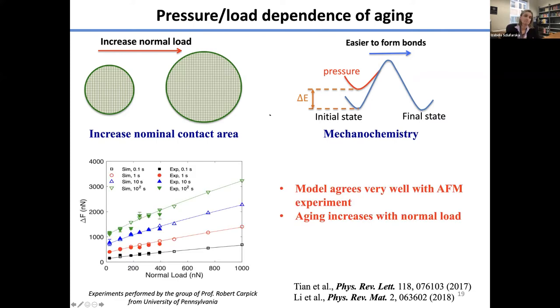So we included mechanochemistry. We have also included the fact that if we have a single asperity and we increase the normal load, the nominal contact area is going to increase as well. So we're going to have more of these bonding sites. So we put it together, and again, started with a single asperity, and we were able to compare to Rob Carpick's experiments again. So that allowed us to validate the model, and you can see that we have very good agreement. The model works very well.